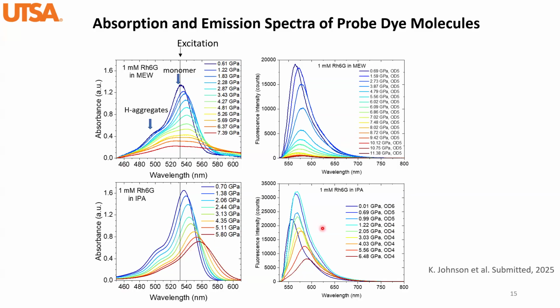And in the case of fluorescence of rhodamine 6G in IPA, we have seen that there's a reduced intensity. Also, please note that there is a change in the incident power by applying OD filters, but for the same OD filters, we have the same incident power. If you compare emission signal collected with the same OD filters, it means it's actually still a constant drop of the intensity. And also we see a constant redshift, which is also the HOMO-LUMO gap reduced by the high pressures.